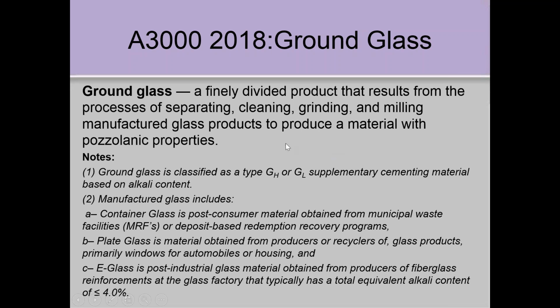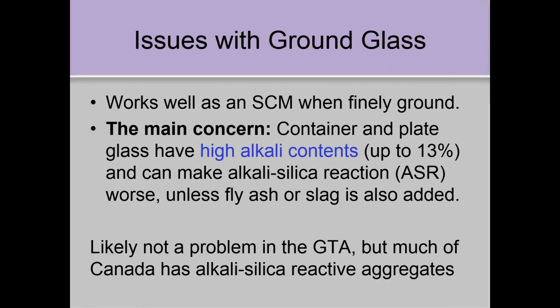So anyway, it's just clean glass that's been ground up to the cement fineness. And there's 2 types of glass. The bottle glass is high alkali glass, so we call that G sub H. And if it's from fiberglass recycling, it has a lower alkali, so they call it G sub L. But I don't think there's anybody doing the fiberglass one in Canada. So it's container glass, plate glass are the main components here. And they're very consistent in quality. Container glasses are almost all identical in composition.